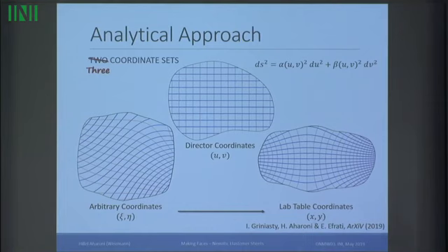And what happens when we actuate the sheet is that at every point the material shrinks by a factor of lambda 1 along the direction U and by a factor of lambda 2 along the direction V. So this just involves taking the exact same functional form for the metric and replacing alpha with lambda 1 alpha and beta with lambda 2 beta. So in a sense, the metric before actuation and after actuation take very similar forms, which will make everything simple in the future.